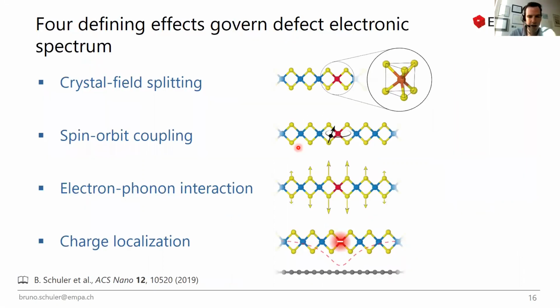Okay, so these are then the four, in a very simple, cartoon fashion, defining things to really predict what kind of energy states you might expect in your band gap. First of all, very obvious, crystal field splitting: how a certain impurity is coordinated in your lattice. You can already figure out from some simple group theory arguments how many defect states you would expect. Spin orbit coupling is very important in these materials, not surprisingly. And electron-phonon interaction is very important too. We will come to this more towards the end of the talk. And as we have just seen before, charge localization is very important.